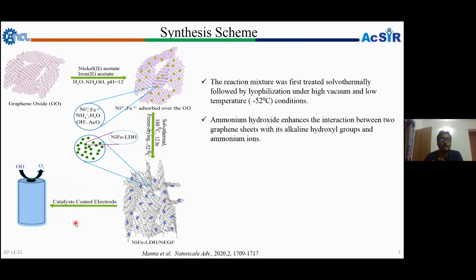So here is our synthesis. First we use the graphene oxide as a substrate, then we use nickel acetate and iron acetate at a particular pH condition, around 12, using ammonium hydroxide, which can act as a reducing agent for the metal precursor, as well as the nitrogen dopant, and as well helps with the self assembly structure formation for the 3D structure. First we sonicated it for a long time, around 10 hours, so metal particles are entering. After that we did a hydrothermal solvothermal treatment at 180 degrees for 12 hours, and after that we applied the freeze